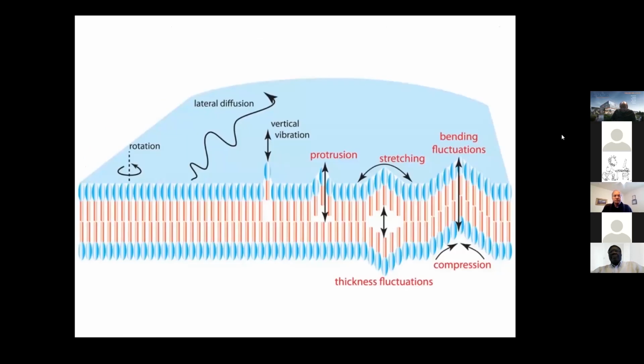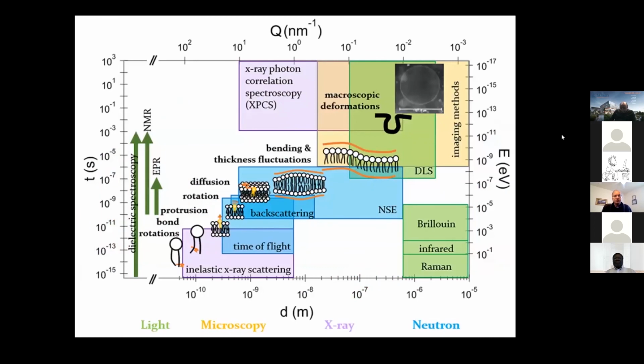And this is where neutrons come in, because frankly, there is no other technique that gives you access to membrane fluctuation. So this is a very simple schematic of a membrane, a lipid bilayer. There are several ways you can have motion on this: bending fluctuations, stretching, protrusion, and thickness fluctuations. And neutron scattering actually sits right in the sweet spot of how we can measure those membrane dynamics.